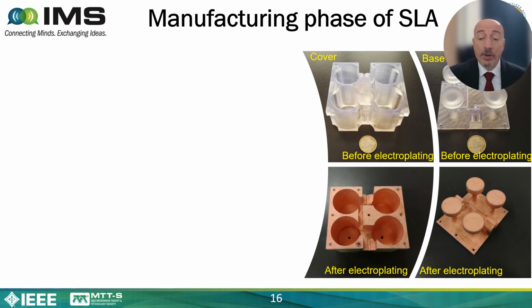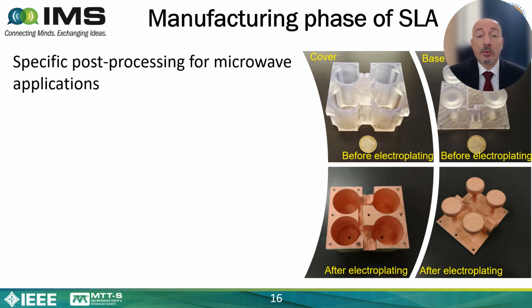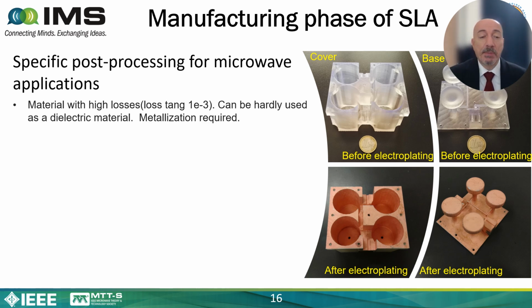In addition to that, for our filter, we have also specific post-processing. This specific post-processing is because this is for microwave applications. I will explain it better. The plastic material produced by this technology is plastic, and so it could be, in theory, used as the dielectric material, but unfortunately the loss tangent is quite high. So if you use it as the dielectric material, you have a lot of losses, and usually this is something undesired when you are working with microwave components.